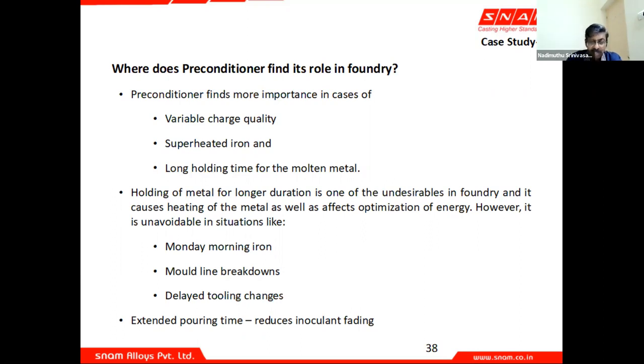Molding line breakdowns result in the metal waiting for the mold. Naturally, the nucleation potential is lost, or a delay in tooling changes, pattern changes sometimes gets delayed. You try to fit the pattern, then realize there are some repairs to be done on the pattern, or there is some issue. So all these lead to holding of the metal, and that extends the pouring time.